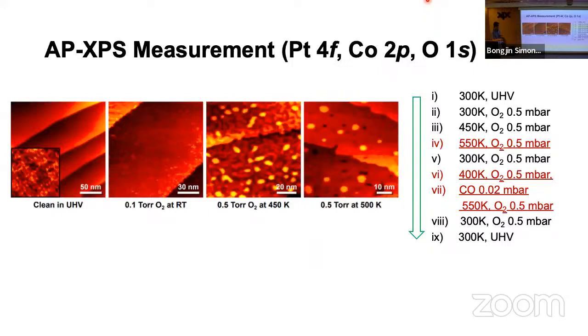under UHV, you prepare very nice STM images, very clean and sharp. When you introduce about 100 millitorr of oxygen, you start to see very small changes, but not a lot. But when you introduce about 500 millitorr and increase the temperature, you start to see this. It's not even clustering. Actually, this is almost like a solid oxide being formed on the terrace. And also this step is completely ruined.